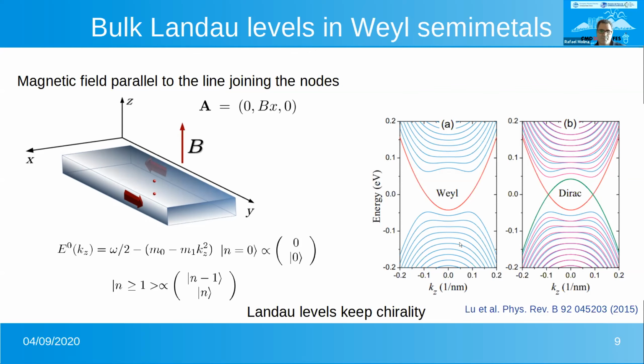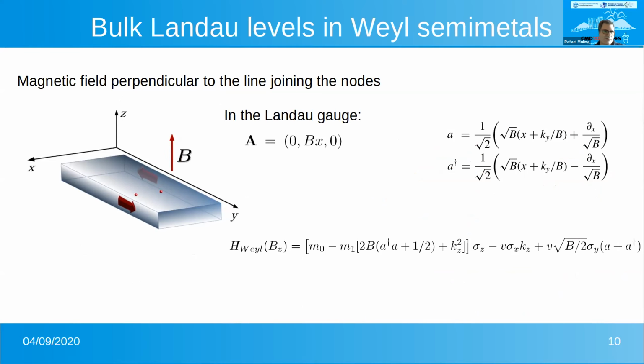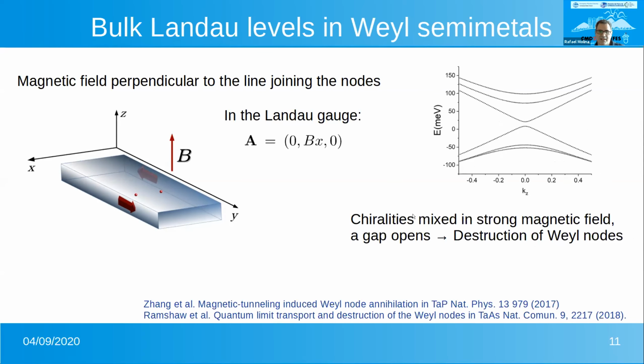But the Landau levels keep some chirality in this direction. If, instead of the parallel direction, we put the magnetic field in the perpendicular direction and try to find bulk Landau levels, we can do a similar transformation to creation and destruction operators, and this will be the bulk Hamiltonian. And here the chirality is mixed. This cannot be solved analytically, or at least I don't know how, but it can be solved numerically, and you find the destruction of the Weyl nodes. And this has been shown experimentally.